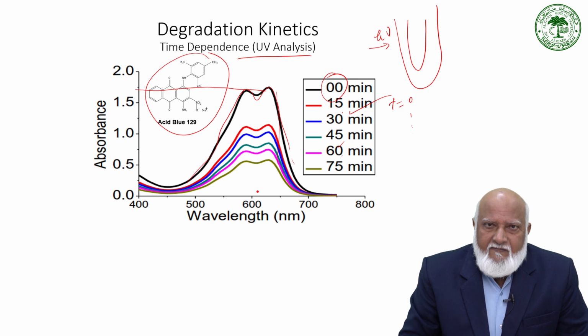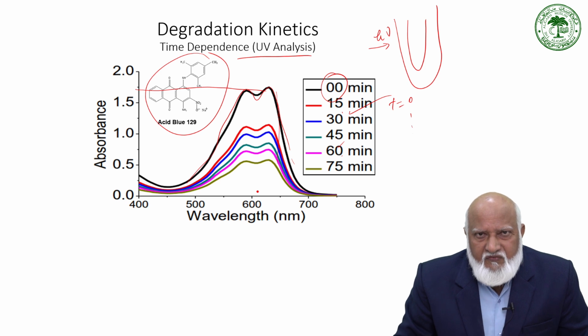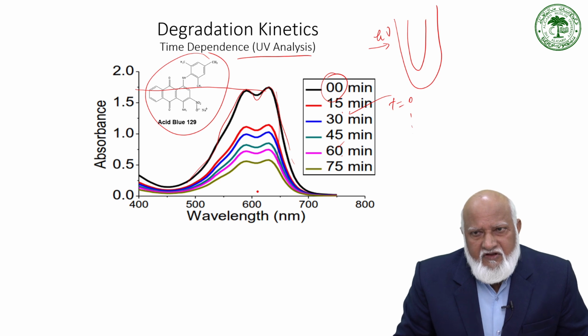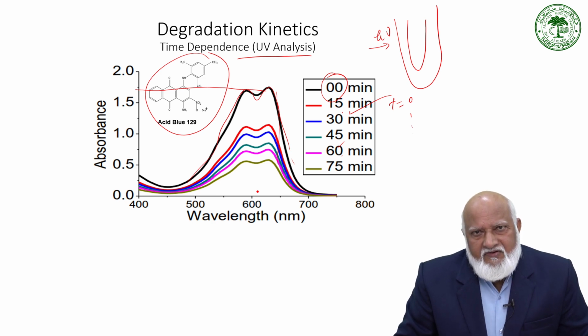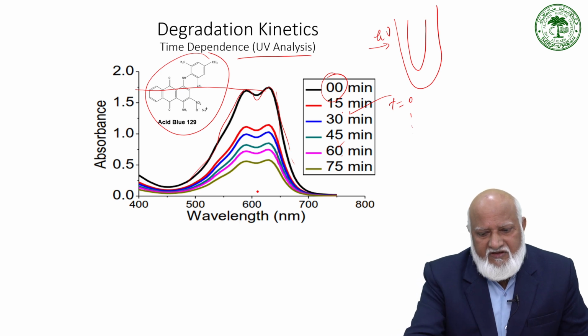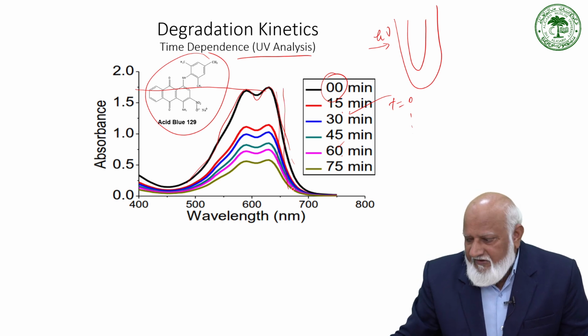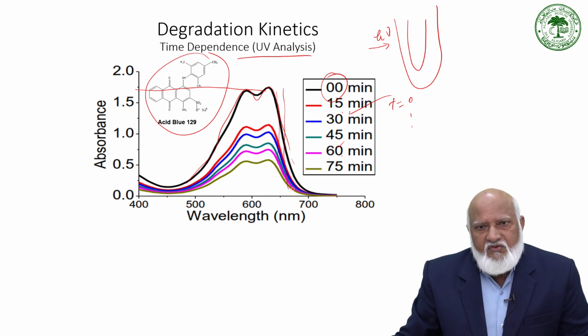So this is a follow-up of a photoreaction of a dye derivative such as Acid Blue 129 using a UV spectrophotometer in a photoreactor, which consists of an immersion well photoreactor, aqueous solution, light on, air bubbling, quiet stirring, collecting sample, centrifuging, and then following by UV. And we can see the decrease in absorbance, decreasing the color of the solution.